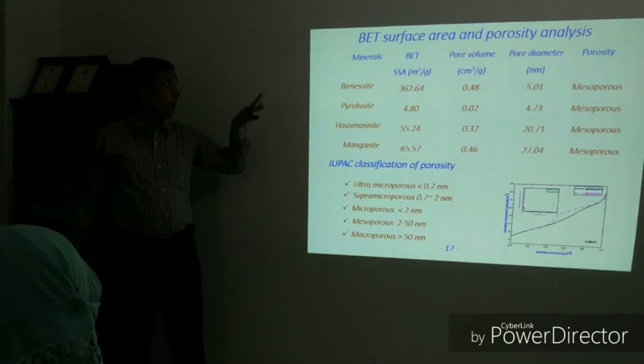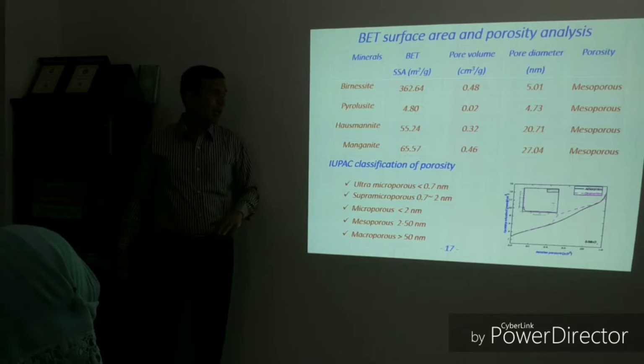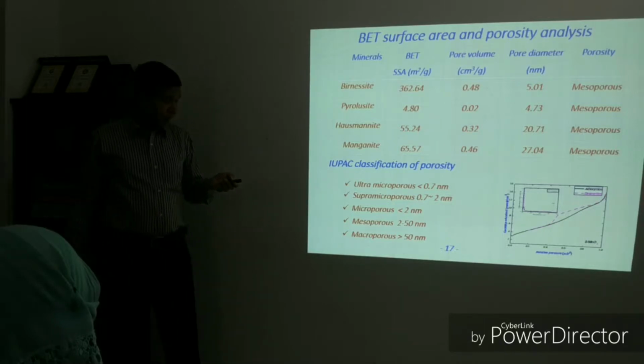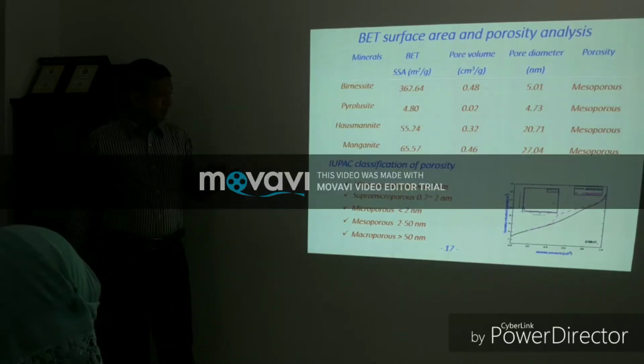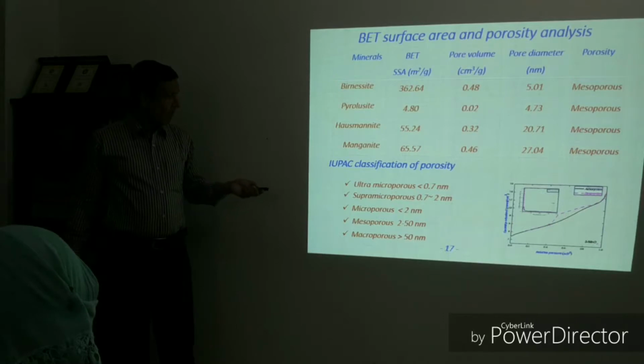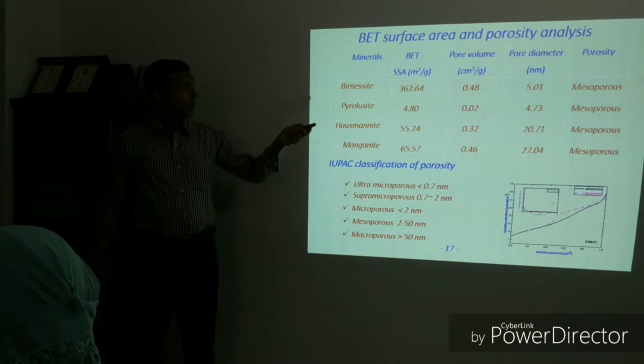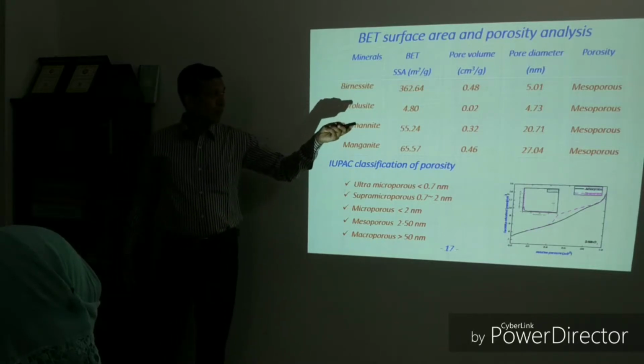Then BET surface area and porosity analysis. From this table, we see that the BET surface area for birnessite is higher than other surfaces, and if we compare the IUPAC classification of porosity, we see that pore diameter is within the range of 4 to 27 nanometers. It means that all substrates are mesoporous in structure.